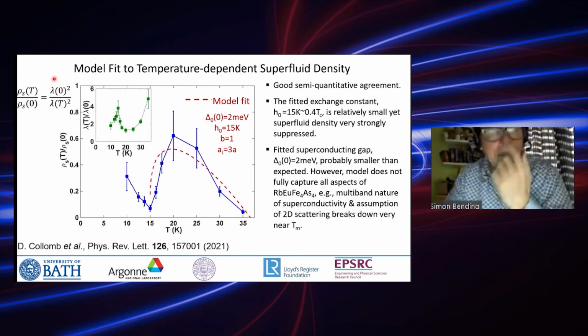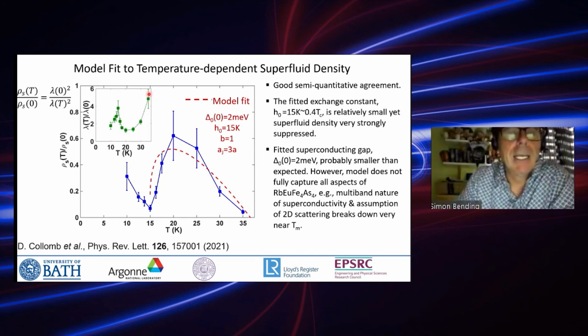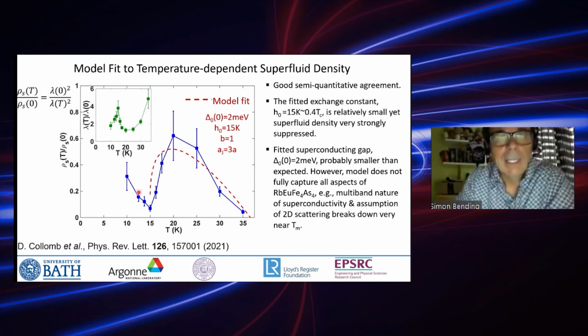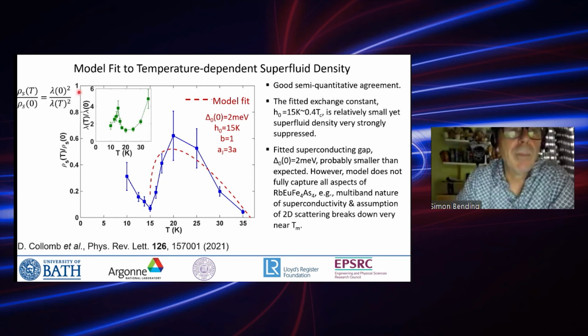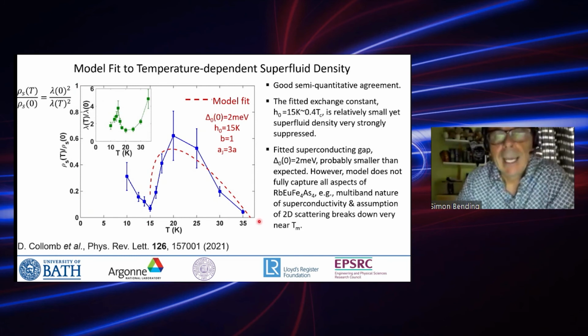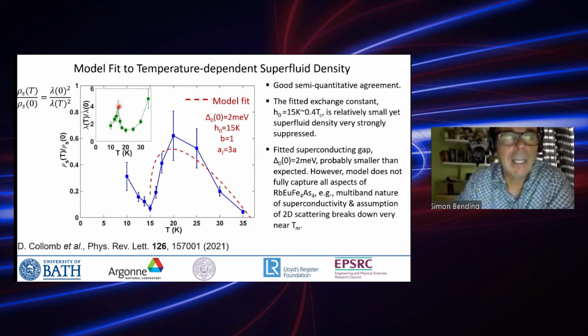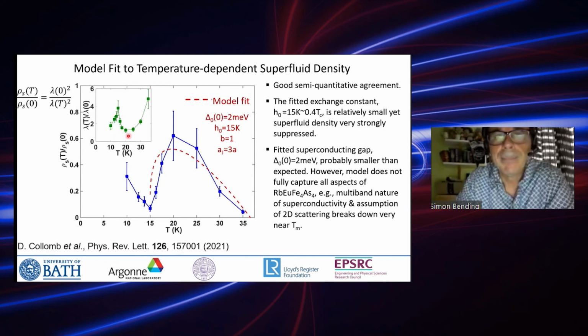So in order to compare the model with the theory, we first have to take the penetration depth data, lambda, and convert it to something describing the superfluid density, and we can easily do that. If we construct lambda naught over lambda T squared, this corresponds to rho_s(T) normalized by some value of rho_s naught. So I plotted that here. This is rho_s(T) normalized by rho_s naught here, and this is the temperature T. And you can see that we now get a strong suppression of the superfluid density at the magnetic ordering temperature, which is the inverse, if you like, of the enhancement of the penetration depth at the ordering temperature.